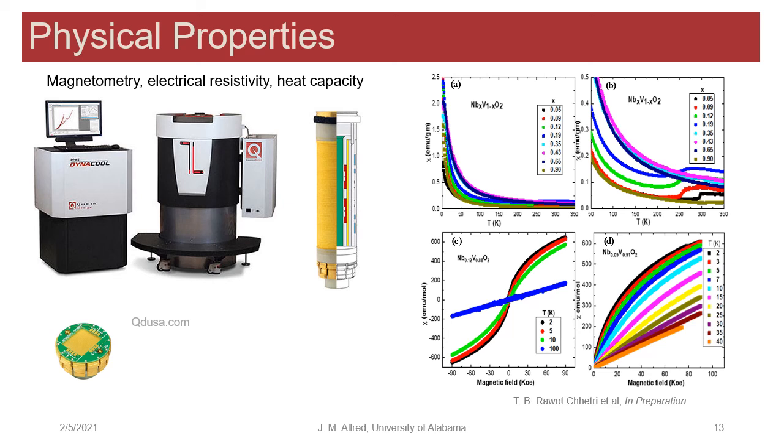So then you can see on the right, we have all these different magnetic measurements. We can see some kind of magnetic transition, depending on if you're looking at temperature or field. You have multiple degrees of freedom. We also look at things like electronic transport that tells you it's a metal or an insulator, which can tell you a lot about something. It's electron count, how are things bonded? Those should match what you see in the properties. You can look at heat capacity, which helps us learn more about phase transitions.